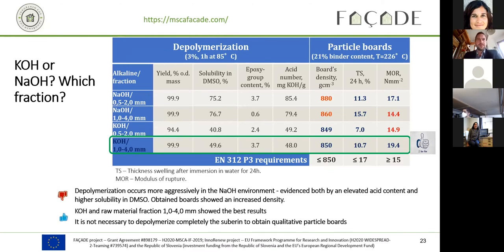The last preliminary parameters we tested were which alkaline and which fraction of birch outer bark we should use. We tried sodium hydroxide and potassium hydroxide in several fractions, concluding that depolymerization occurs more aggressively in the sodium hydroxide environment, evidenced both by an elevated acid content and higher solubility in dimethyl sulfoxide. Obtained boards showed an increased density as well, but potassium hydroxide and raw material fraction 1 to 4 millimeters showed the best results, and we concluded that it is not necessary to depolymerize the suberin completely to obtain qualitative particle boards.